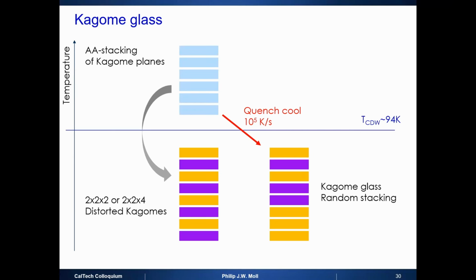So you quench cool this at, let's say, 100,000 Kelvin a second. You don't give the system kinetically the time to find its happy 2 by 2 reconstruction, okay? Because all of these sliding motions, it essentially is a translation of the entire plane. So what if the system just doesn't have enough time and enough kinetic energy to actually reach this, and you kinetically block a state that is metastable, which is what we call Kagome glass? I think this sounds nice and well-selling, but really what it means is it's a random stack. There's no order in the out-of-plane direction.